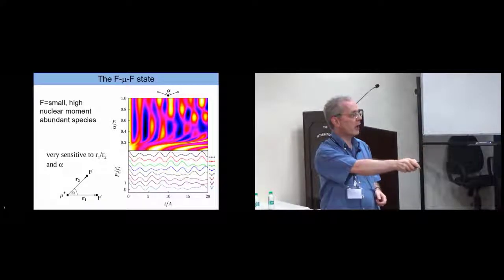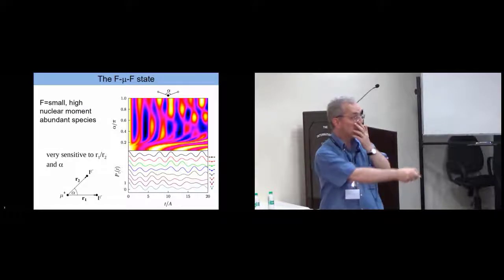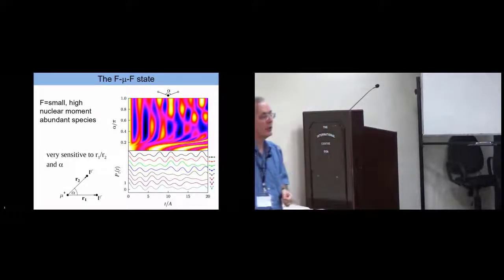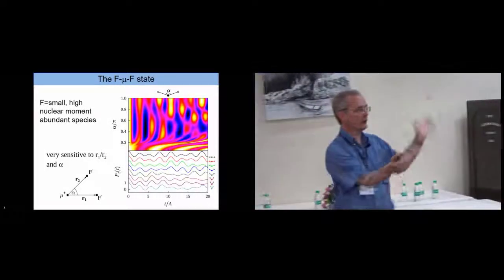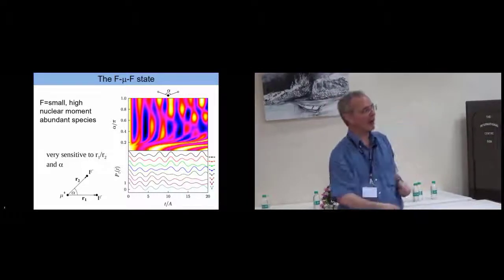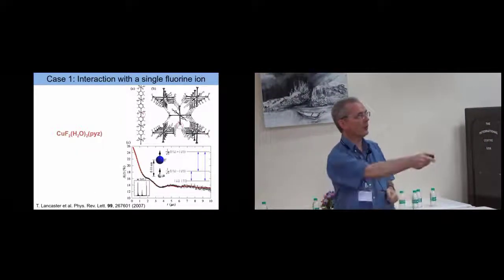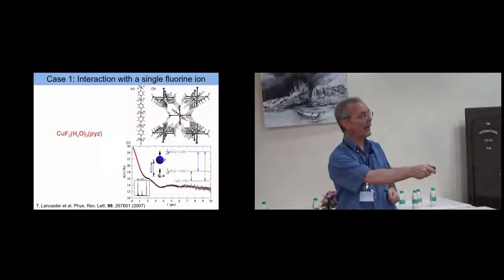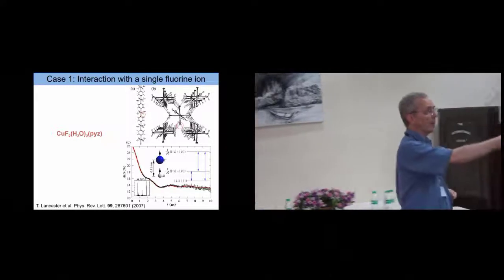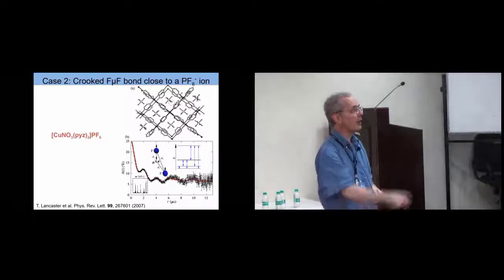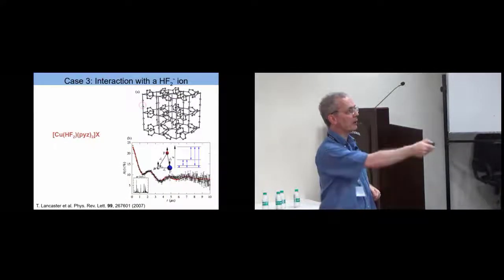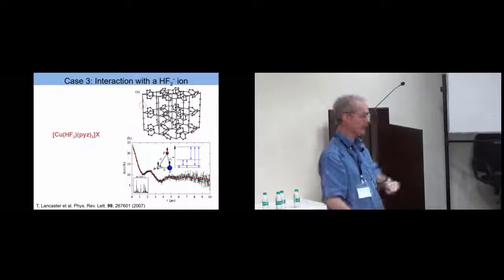These oscillations are very, very sensitive to the fluorine muon fluorine bond angle as well. The shapes of the oscillations change, which you can simulate in a computer. Obviously, you can't get the bond to go as far around as that. But just to give you a few examples, in some complicated organic materials, we've been able to localize the muon site in this material where you actually interact with a single fluorine ion, in this one where you have an F-mu-F bond, and also in this material where you have an HF2 minus ion.